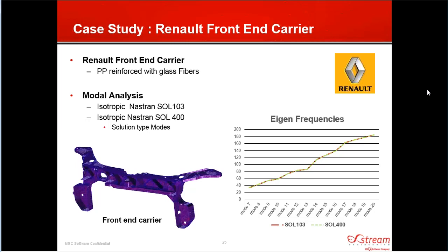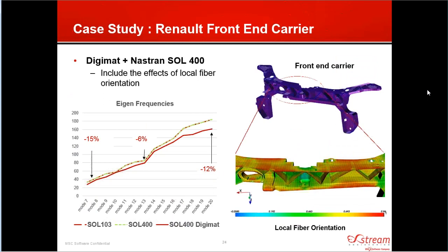You can see here from the chart on the right that we see a good correlation between the various eigenmodes for these two different solution types. And in addition, when we add Digimat into Nastran Solution 400 and we take into account that variety of local fiber orientations, we see an increase in the accuracy of the modal analysis. We start to see those modal frequencies shift. The part is actually a little softer than we expected because now we have these areas of randomly aligned fibers, and you get a more accurate solution using Digimat plus Solution 400 relative to the traditional 103 approach.